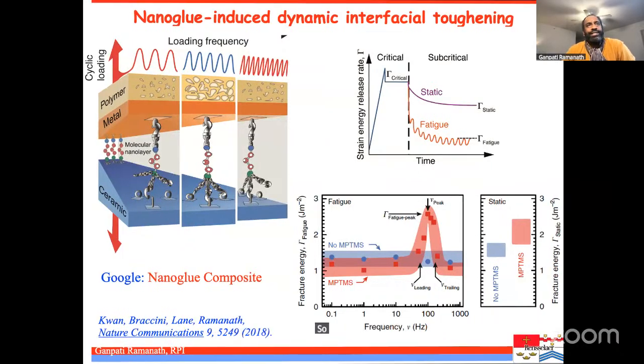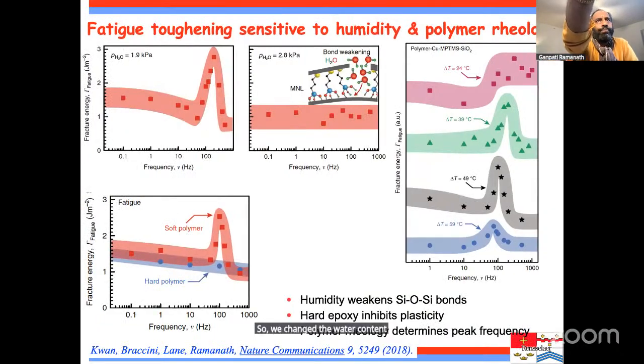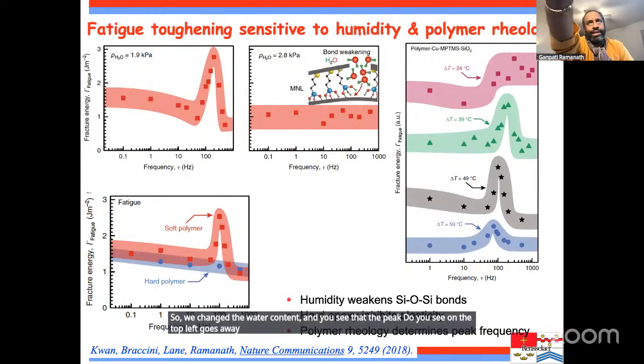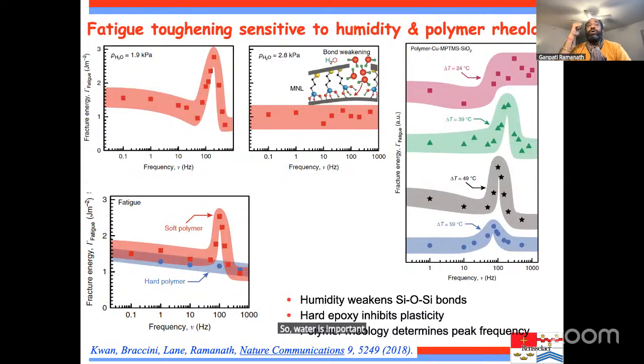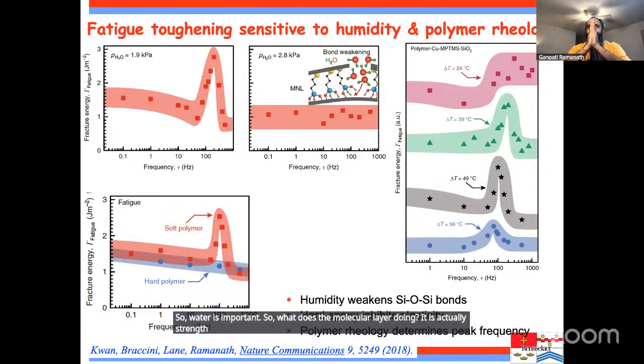So we change the water content, and you see that the peak, you see on the top left, goes away. It becomes flat immediately in the middle. So water is important. So what is the molecular layer doing? It is actually strengthening the interface, and strengthening the interface is an important condition.